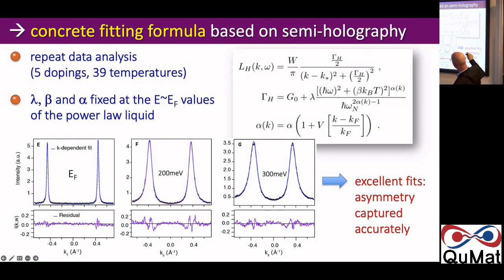So we repeat the data analysis, 5 dopings, 39 temperatures. We fix the other bits of this power law liquid to be the same as they were at the Fermi level. And then we don't actually have any more parameters to fit experimentally than we did in the old model. That was the clever thing coming from the collaboration with Henk and Inea. So we have excellent fits, and as you can see, the asymmetry is just rolling out perfectly. And the only thing we're able to tweak in this fitting is what the value of this V is. In this case, we took it to be equal to 1, which is what is demanded by the theory.